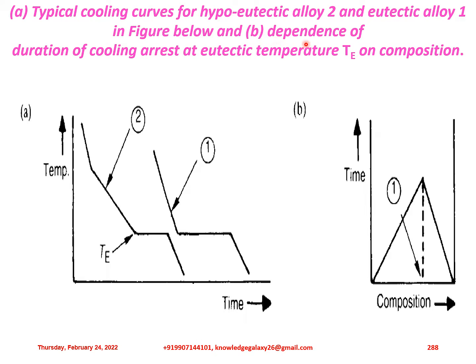So in this current slide, typical cooling curves for hypoeutectic alloy 2 and eutectic alloy 1 are shown in figure A, and B is shown as dependency of duration of cooling arrest at eutectic temperature T eutectic on composition. So in this figure A, the cooling curve for alloy number 2 is shown, and this is the cooling curve for alloy number 1. As you can see, alloy 2 freezes over a very small range of temperature, and as soon as the temperature reaches the T eutectic temperature, it abruptly freezes and solidifies completely.